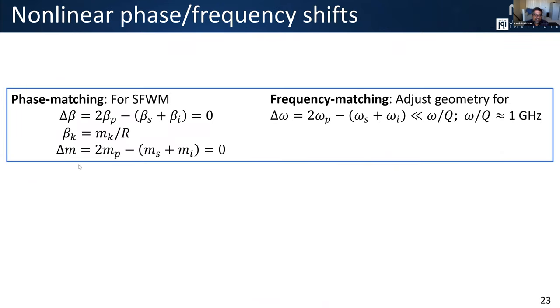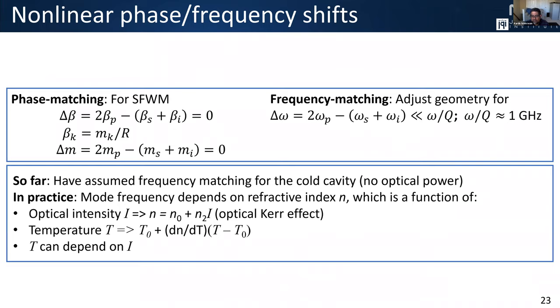We have these two criteria — mode number matching and frequency matching. Implicitly I've been saying that resonance frequencies are independent of how much light we put in. But for chi-3 media, resonances shift when you put more light in because of the Kerr effect — you have an intensity-dependent refractive index and also thermorefractive effects. So we do have to take into account these intensity-dependent frequency shifts depending upon which regime we're operating our devices in.